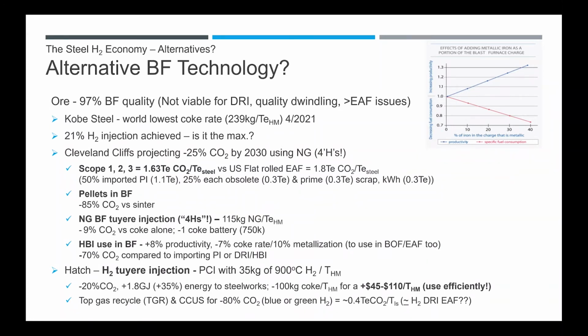Hatch, on the other hand, have looked at hydrogen tuyere injection with PCI using 35 kilograms of 900 degrees centigrade hydrogen, 20% reduction in CO2, 1.8 gigajoules, which is 35% increase in the energy to the steelworks, and 100 kilograms of coke reduction, but that's going to cost up to $110 per ton.